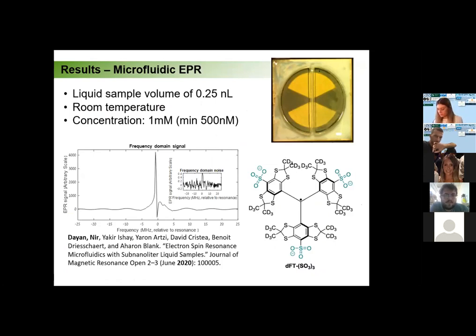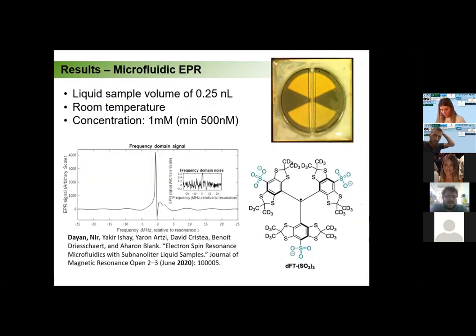Okay, another application is the microfluidic EPR. Here we took the resonators and we put the microfluidic channels on them. And we can also put some kind of grid that has very small pores if we want. And then we took this stable radical, and we measured a liquid sample volume of 250 picoliters at room temperature, at the concentration of 1 millimolar, and it has the sensitivity to measure also 500 nanomolar.